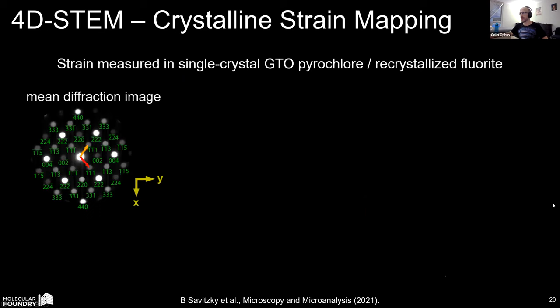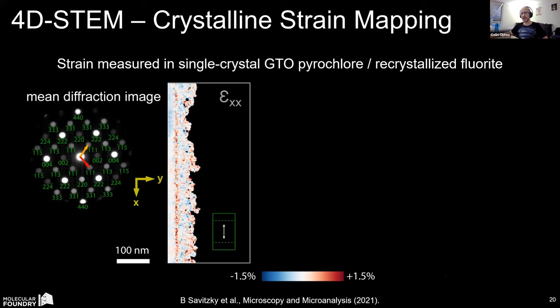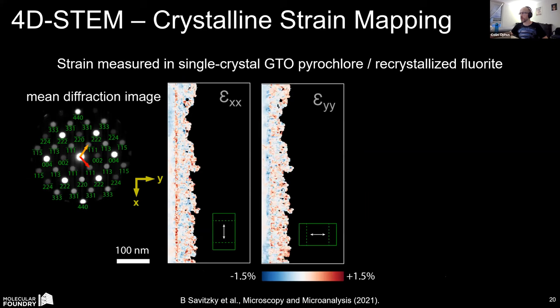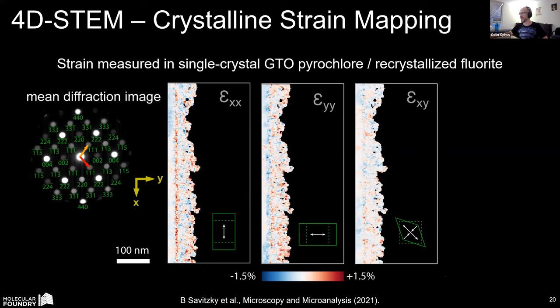So in that pyrochlore sample I showed previously, here's the indexed diffraction pattern in the single crystal pyrochlore region. And I'm just showing the strain in the vertical epsilon XX direction, the horizontal epsilon YY direction, and then the shear strain, the XY here. So you can immediately see some interesting features. That red line in epsilon XX running vertically, that is precisely where the amorphization front reached into the material. And you initially recrystallize with a lot more disorder, and then it settles down within about a 5 or 10 nanometer area, and you grow these recrystallized fluorite grains here.